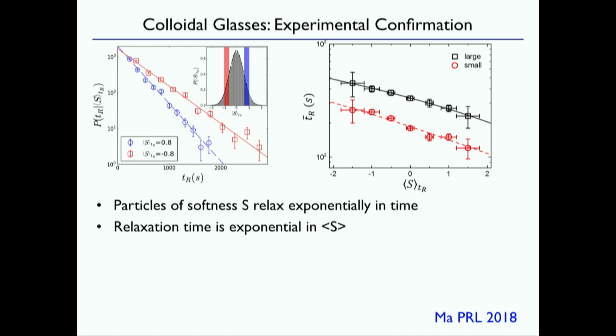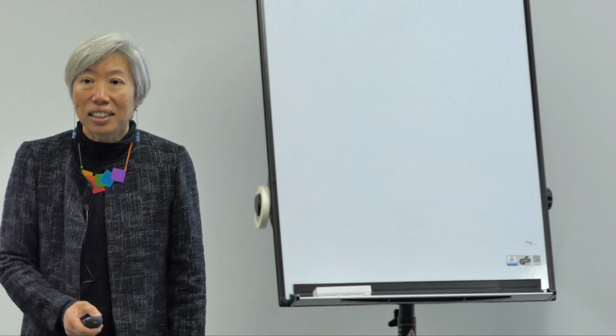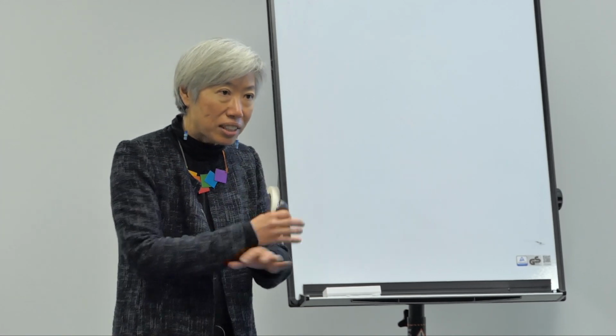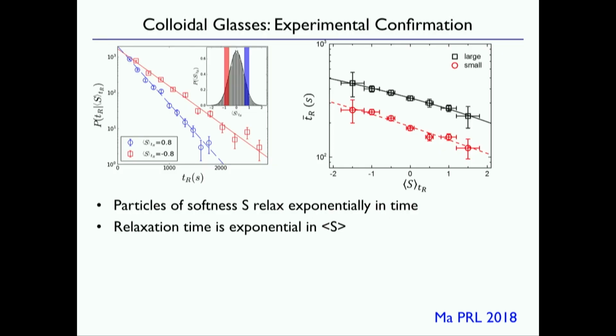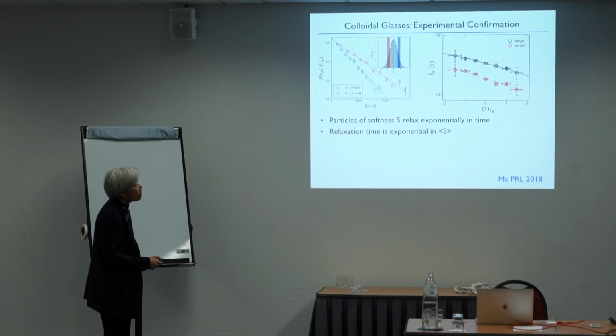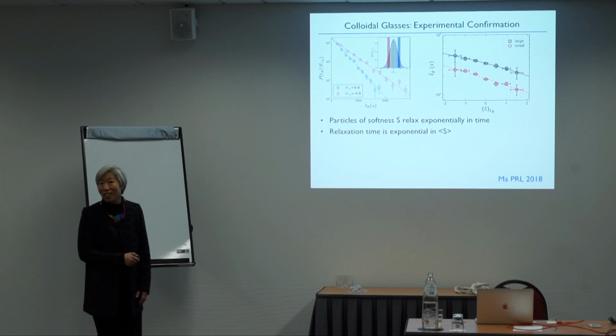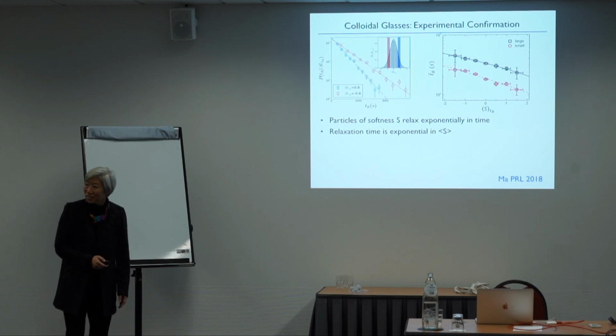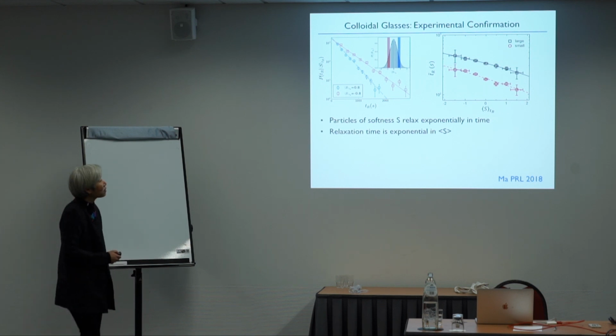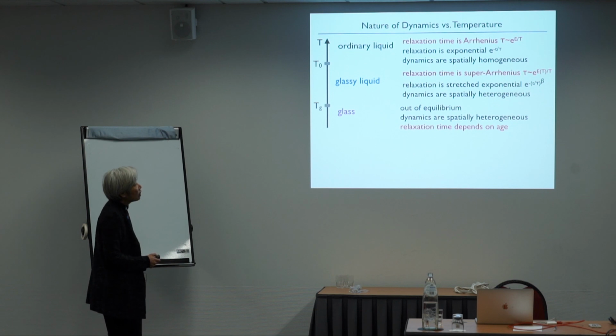So it predicts the relaxation time. And we actually have some experimental confirmation of this. We applied this to colloids. Colloidal systems, just do video microscopy, 2D system. This is with Arjun Yodh's group at Penn. And what you see is the average relaxation time as a function of softness, and it is exponential in the softness, as we find in the simulations. So this seems to be working. All right, so now we understand these three things.